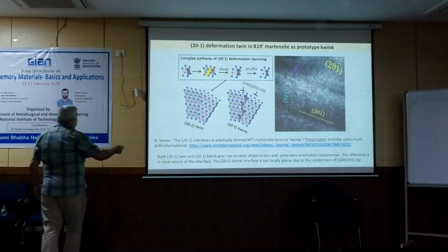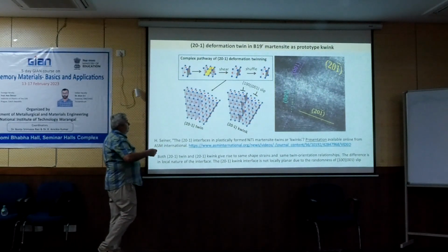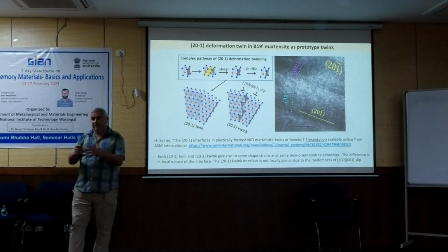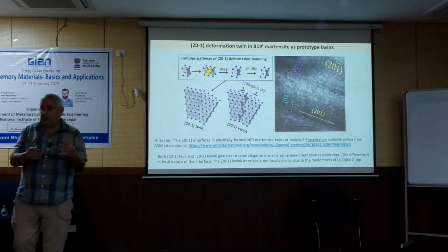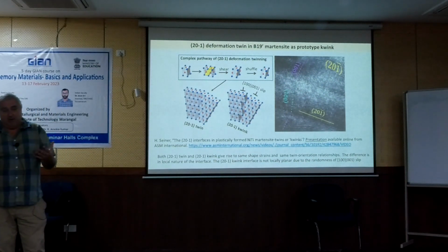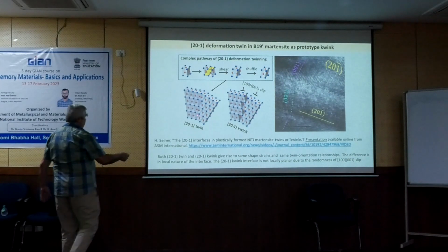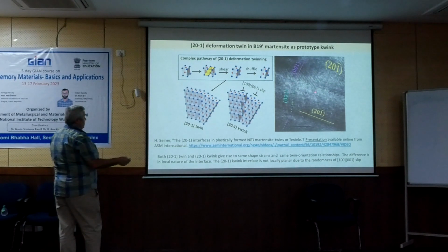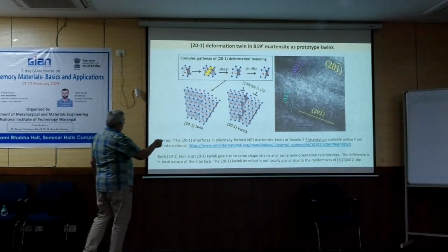Here, if we use twinning, we can characterize this twin by a finite deformation gradient. These deformation gradients for each alloy are known; they depend on the type of martensitic transformation, and they will tell us that if this twinning occurs in the material, I would see them, and the strain would be compatible here.